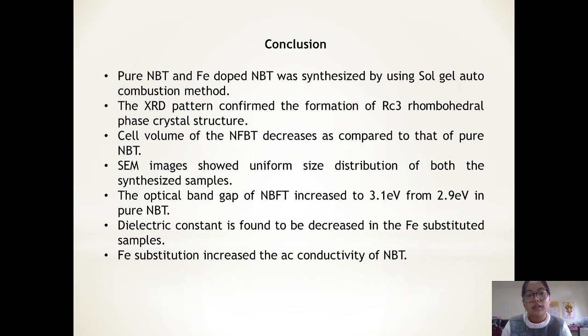The optical band gap of NBFT increased to 3.1 electron volt from 2.9 electron volt in pure NBT. Dielectric constant is found to decrease in the iron-substituted sample, and the Fe substitution increased the AC conductivity of NBT.